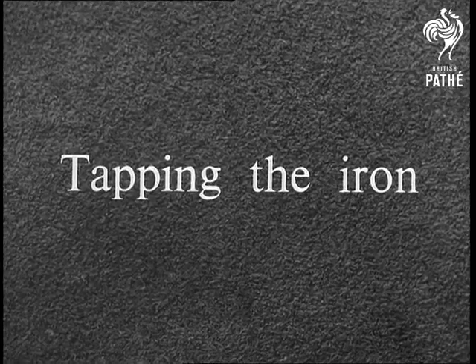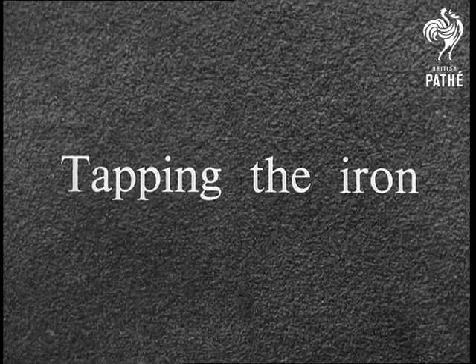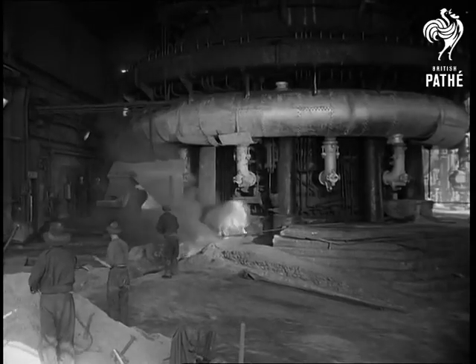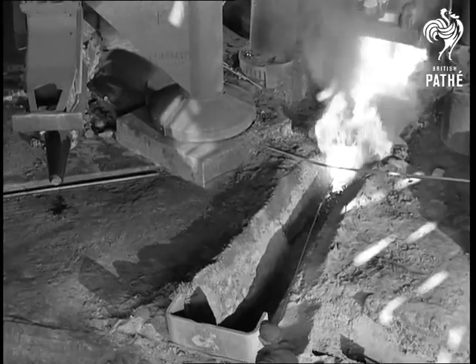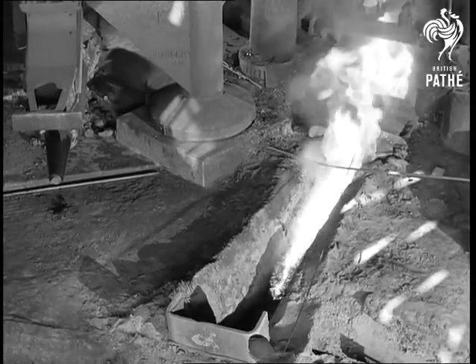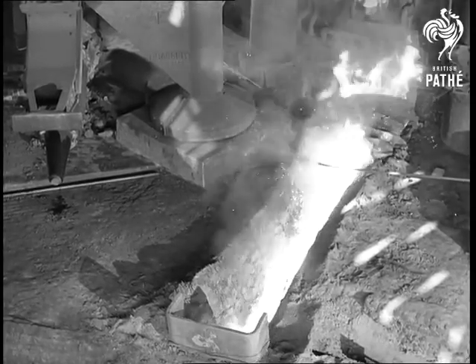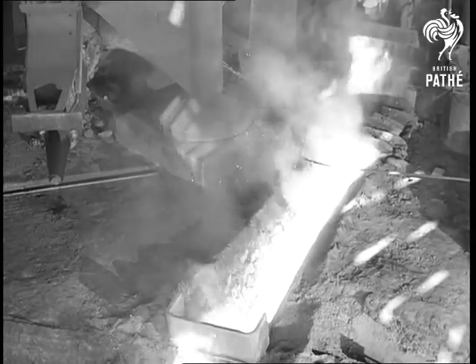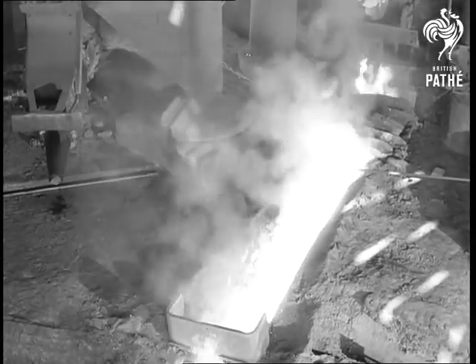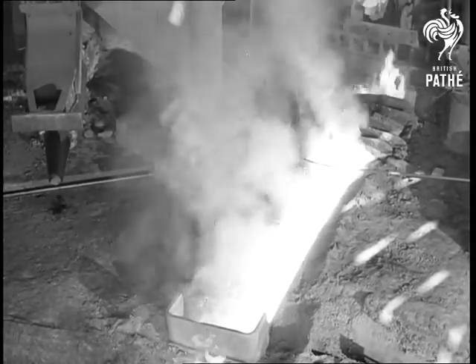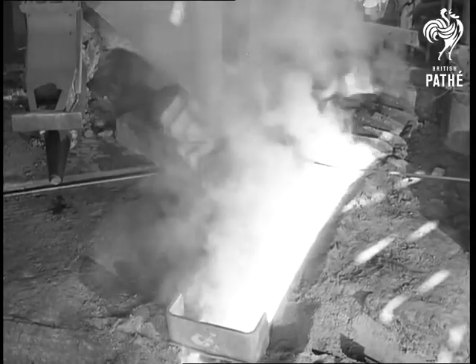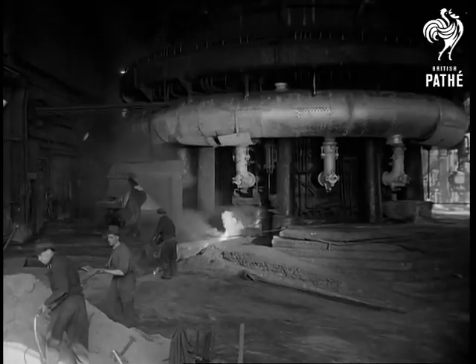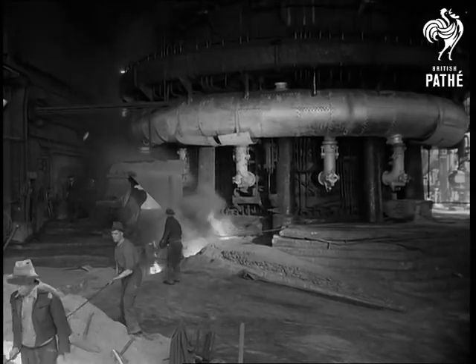In tapping the iron, the fire clay used previously for sealing the tap hole is first drilled through. Then, oxygen gas from a tube is directed onto the metallic crust that forms at the bottom of the hole. The hot crust burns in the oxygen, making a hole through which molten iron flows out freely into a U-shaped trough of cast iron lined with fire clay. The three men on the left are now withdrawing the oxygen tube.